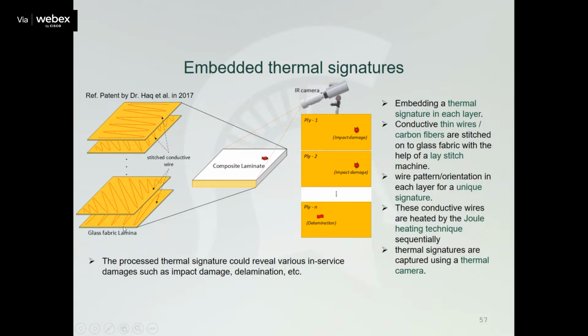And so each layer is going to have its own thermal signature, right? So this brings you a unique signature based on the unique wire pattern orientation at each layer. And you can heat those conductive wires by Joule heating technique and capture that thermal signature using a thermal camera. What does this offer you? Then this processed thermal signature could reveal various in-service damages, for example, impact damage, delamination, and so on. And because it's unique to different plies or different depths, different thickness, then you can get this 3D imaging easily, because it's much, much easier to do the signal processing with these embedded sensors.